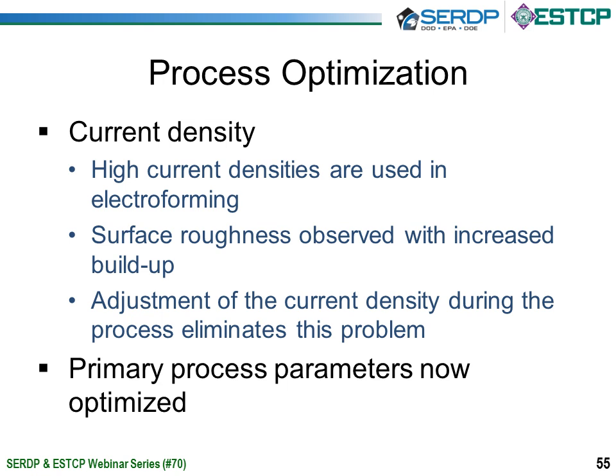And it was found that if at this point you just started to reduce the current density just slightly, the issues were largely resolved. And although the coating rate was diminished slightly, the effects really weren't significant. So these were the three process parameters of interest. The process is now considered fairly stable. All of these parameters have been optimized for the electro deposition of nano cobalt phosphorus for the bushing application.